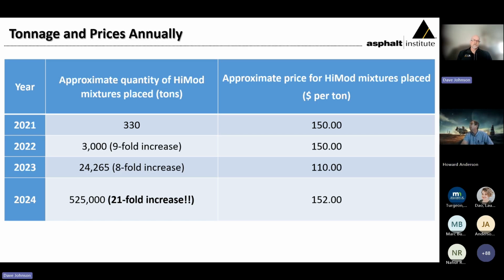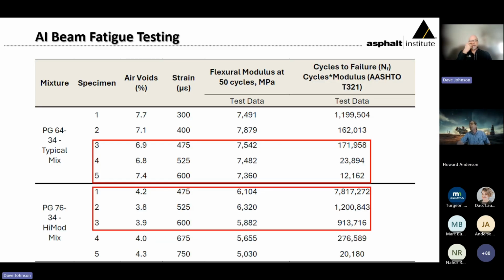Excellent. Thank you, Howard. We did some testing at the Asphalt Institute lab, some beam fatigue testing, and I really want to focus in on the two boxes that are highlighted in red. Notice that we were using a 64-34 Superpave mix, comparing it to the highly modified mix. Also, the Superpave mix was targeted at 7% air voids for those beams, and much like Howard in Utah has done with the Hamburg testing, we targeted 4%.